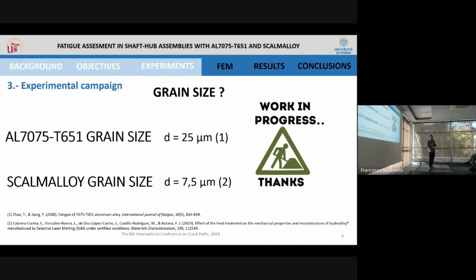At this point, I would have liked to show you the measurements for the grain size, but unfortunately they are still not done, for many reasons. So I apologize for that, but I'm going to use some values that I have found in the literature. Of course, we are working on that, and in the future we will have these results. For aluminum 7075, I have used an average value of 25 microns for the grain size, and for Scalmalloy, an average value of 7.5 microns. This is important because the model I'm going to apply now, the Carpinteri model, depends on this parameter.